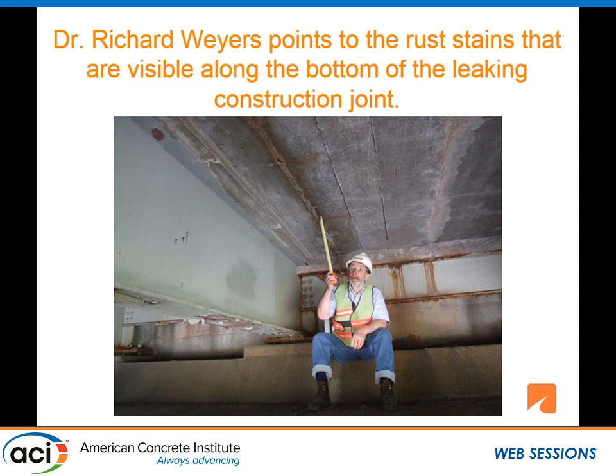And this is a picture of Richard after this deck had this shear failure. Fortunately, no one was injured. It was actually reported as a pothole. But Richard went down to the site south of Blacksburg, and we found three decks that had been reconstructed about the same time in 1992 using the same techniques.